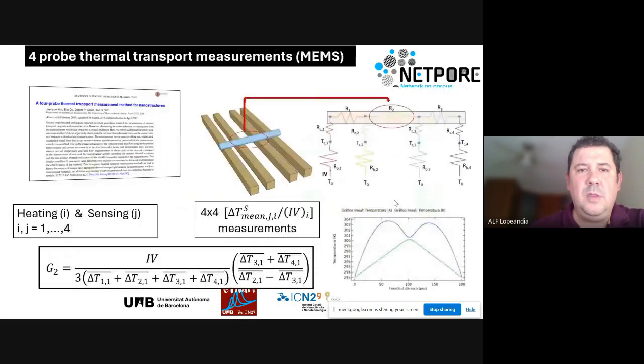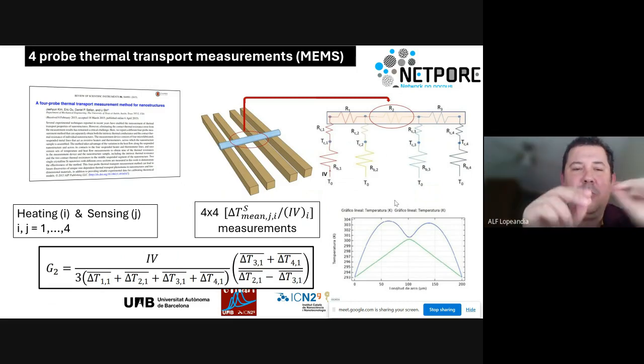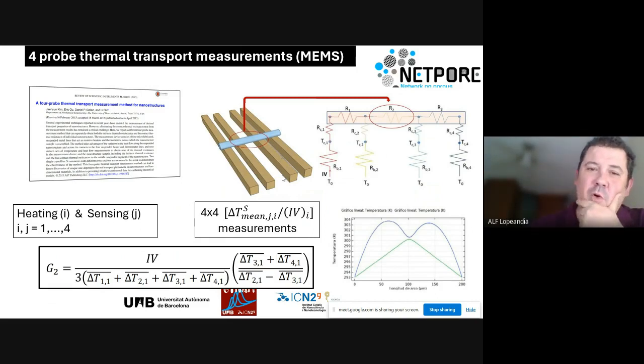Luckily, in 2015, Lishi came again with a very nice structure. This structure is based on four parallel probes that can be heated or sensed independently. Then we have four lines. Each of these lines is a silicon nitride line that is equipped with a metallic, resistive actuator that can be heated up. Now, if we heat up, we have this kind of parabolic profile.